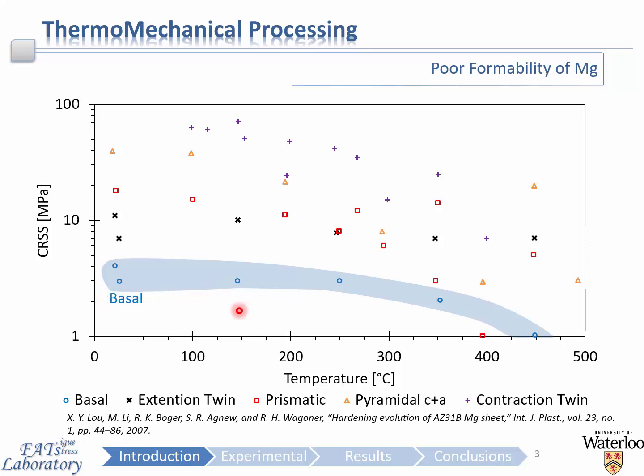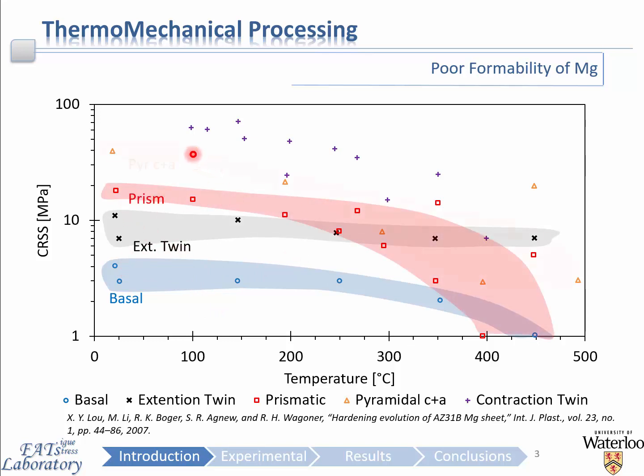If the grain orientation is not favorable to activate basal slip, then extension twinning will be active here in the range of 7 to 10 megapascals, followed by prismatic, pyramidal, and contraction twinning. Von Mises' criterion states that for arbitrary plastic deformation, at least 5 independent slip systems need to be able to be activated. At room temperature, this is very difficult with magnesium, as basal slip is typically what is dominating.